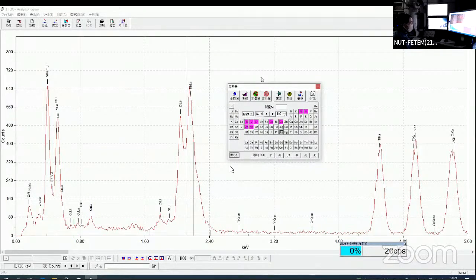So let me introduce our research capability using chromium nitride nanosized particles doped with many cations. Okay, so this is an EDS. Can you see the EDS spectrum? I think I'm sharing an EDS spectrum with you. Yes, okay, good. This is an EDS spectrum obtained a few minutes ago from a small grain with a diameter of 10 nanometers. You may see peaks of cations, vanadium, titanium, and also niobium, zirconium. They are dopants, and also chromium and titanium L lines. But those L lines overlap with the oxygen K and also nitrogen K peaks. So we don't know whether oxygen and nitrogen are inside the sample or not.